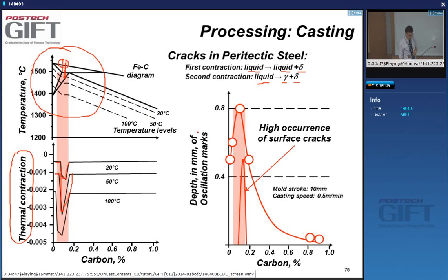And what people also measure is, for instance, the depth of what we call oscillation marks. You remember that I said the casting unit moves up and down with a certain frequency, on the order of a centimeter. Every time it goes up and down, you will have stresses, because when it moves down, it's together with the slab, and moving up, you stress the slab. And this oscillating motion also leaves surface marks, which we call oscillation marks.